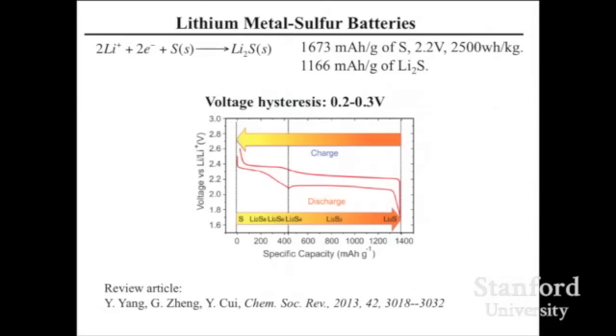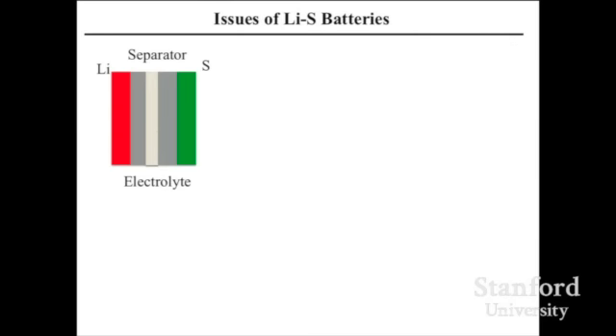Sulfur can be charged and discharged right here. This is the voltage versus capacity. Once you put lithium into sulfur, they start to form a polysulfide phase, soluble in the electrolyte, which later becomes lithium sulfide. Indeed, it's very, very hard. People have worked on this sulfur cathode for a few decades.